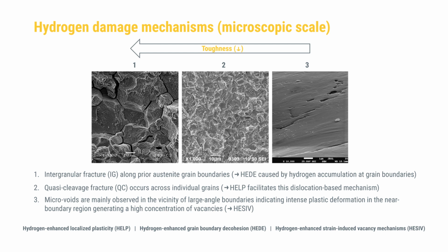Hydrogen-induced cracking is difficult to detect in steels, and particularly the underlying triggering mechanisms are extremely difficult to detect. The phenomena related to hydrogen-induced cracking are playing on atomic scale, on individual lattice planes at interfaces like grain boundaries or particle interfaces that are nanometer sized. So it is very difficult to do measurements or detect hydrogen at such features from an analytical point of view.